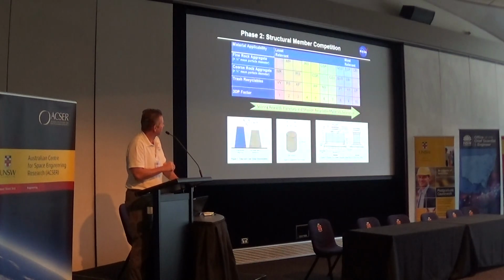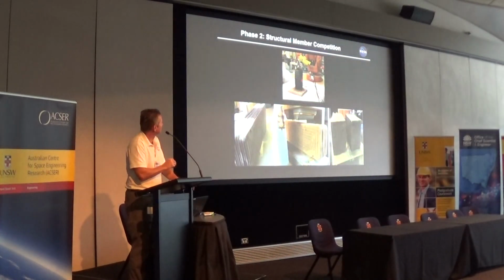devices or structures that they had to build. 300 millimeter cylinder. These are based on ASTM testing standards. So we run an ASTM standard test on this, and this is a C78 ASTM test, and this one is C39, I believe. Here's a cylinder being 3D printed with concrete and a robot arm. Here's a beam that has been 3D printed. Here's the beam in a bending test. It's actually a 4-point bending test, I believe, 2 points below and 2 points above. And then this is the interface where it broke, the fracture plane.